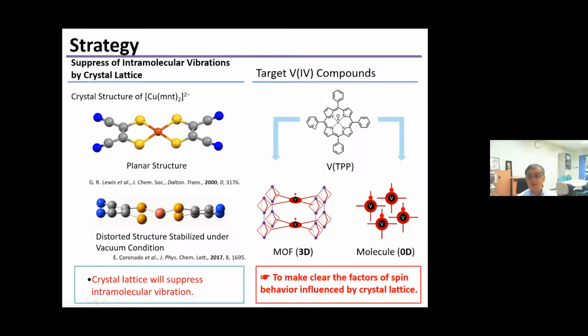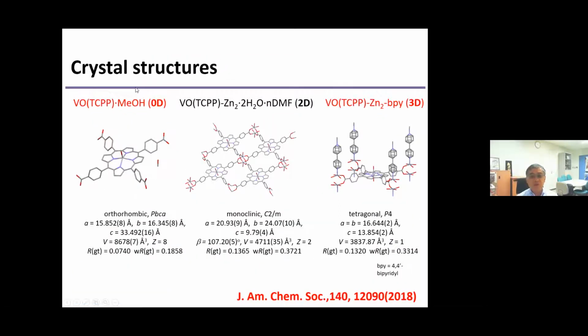So I focus on the oxo-vanadium TPP. In the zero-dimensional soft lattice, we introduce a 3-dimensional MOF of this oxo-vanadium TPP to make clear the factors of spin behavior influenced by the rigid lattice. So we synthesize step by step. The zero-dimensional starting material gets a zinc ion to make a 2-dimensional material, and a bipyridine to make a 3-dimensional MOF. Zero-dimensional, 2-dimensional, 3-dimensional, step by step, I synthesize.